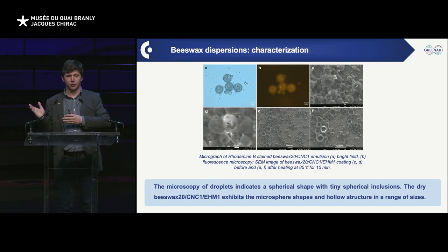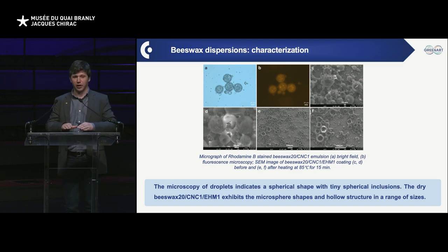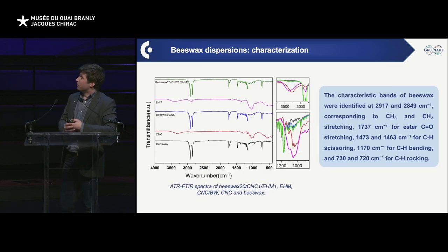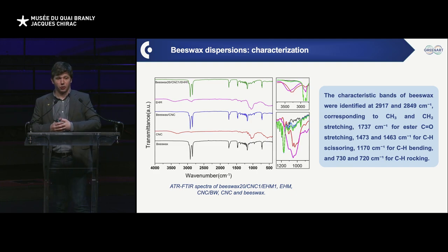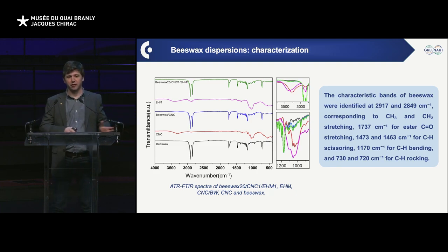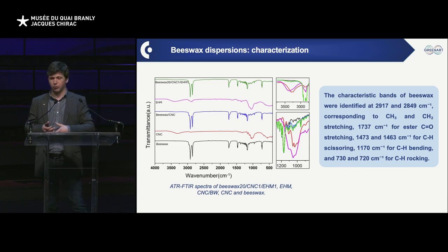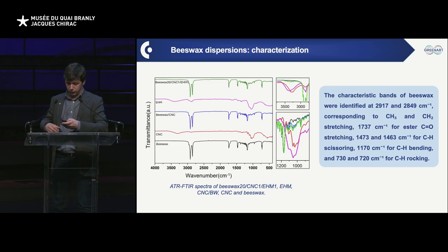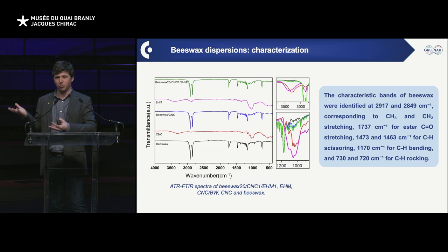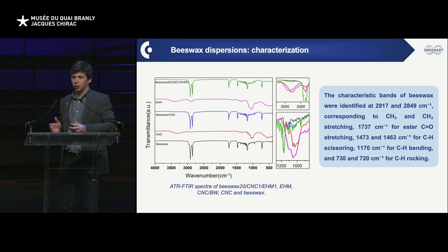So that means if we look at permeation of the system, this is not too bad, essentially. So that will not clog everything like other films would do. That was a positive surprise we got here. We looked, naturally, at, okay, when we do the emulsification, it's a relatively mild process, but things can always degrade, so we looked at the infrared spectra. I will not dig into the infrared spectra because the bottom line here is that not much has happened to the beeswax. It's more or less the same beeswax as we put in the vial when we do the emulsification. So from that, we know that what we mix remains what we mix, essentially.